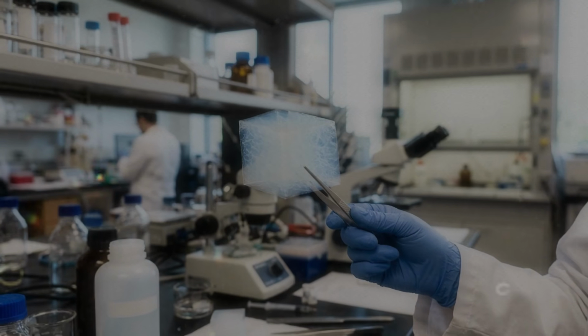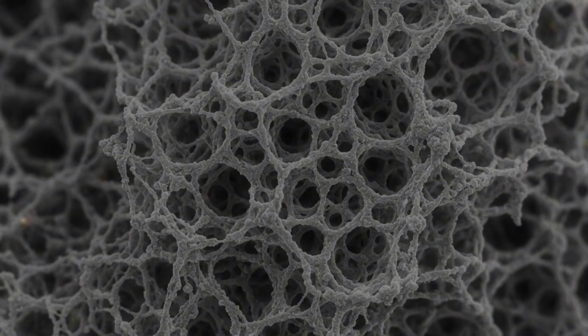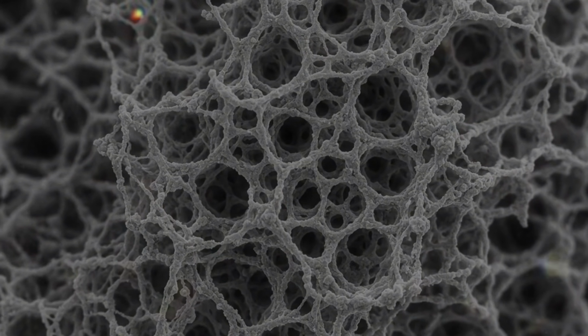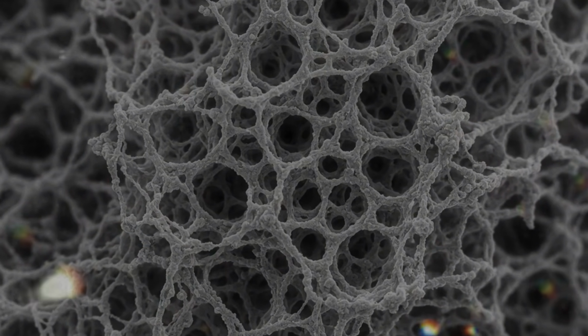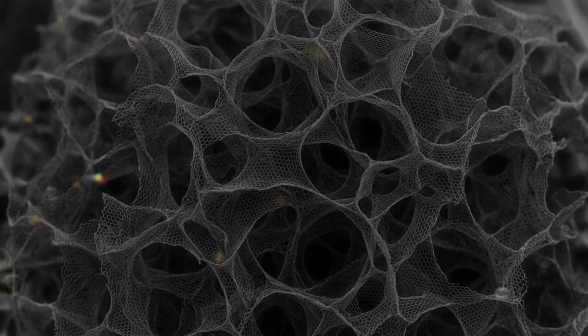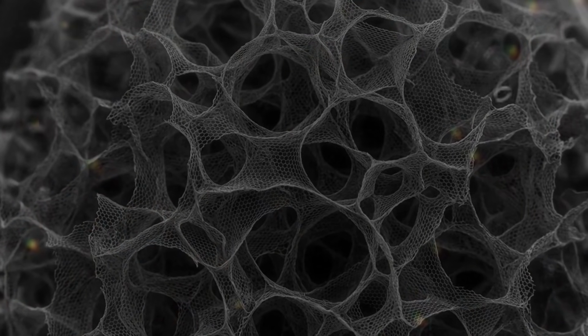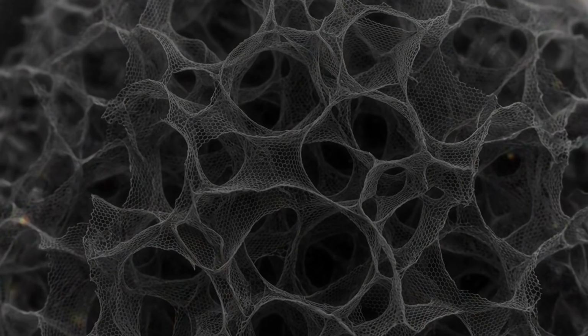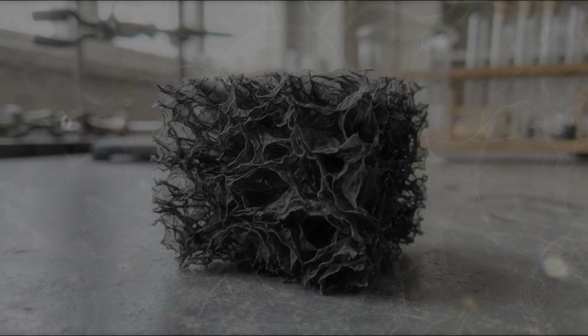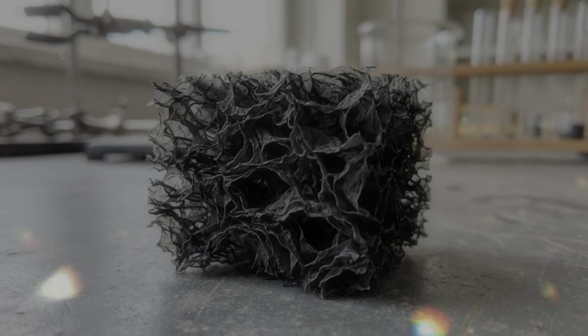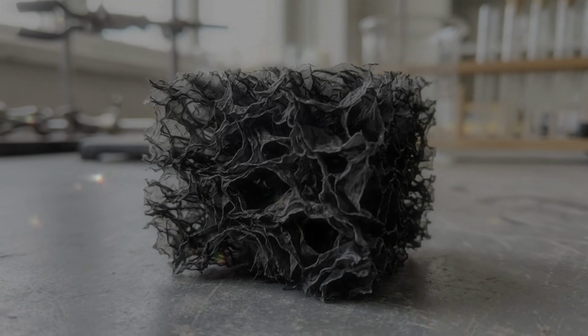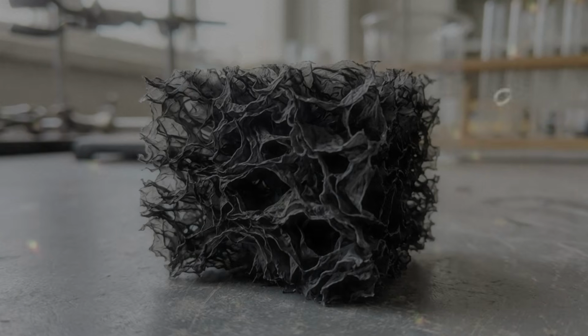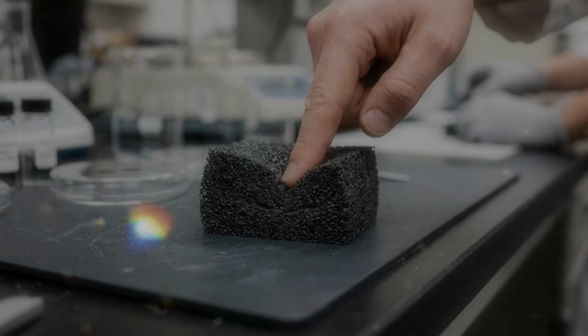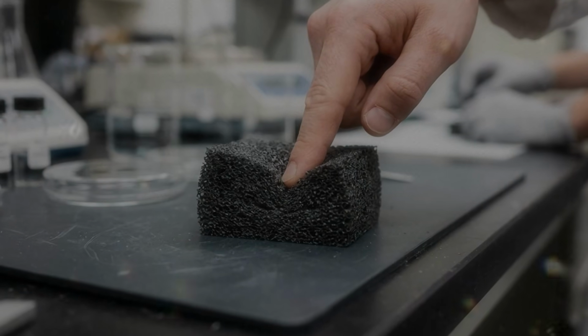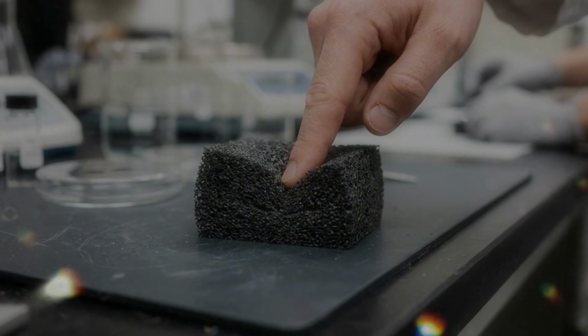The disadvantage is the extra processing. The template must be made, coated evenly, and removed without damaging the final structure. Another approach allows graphene material to grow directly on a metal foam. The metal provides a surface on which carbon layers can form. The metal is then dissolved away, leaving behind a delicate carbon copy. This can produce highly conductive networks with well-connected pathways, though the equipment and processing may be demanding.